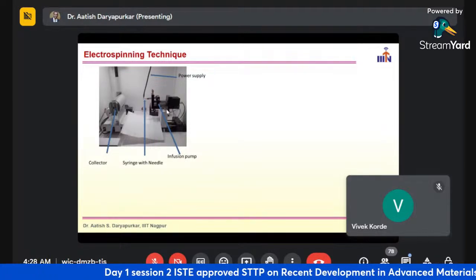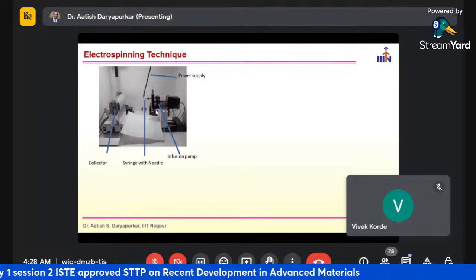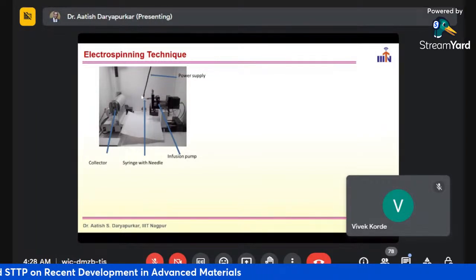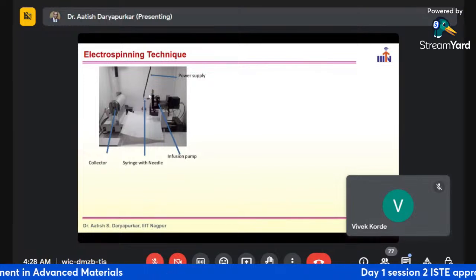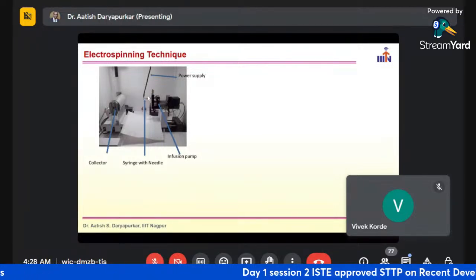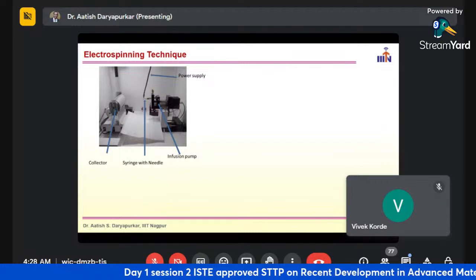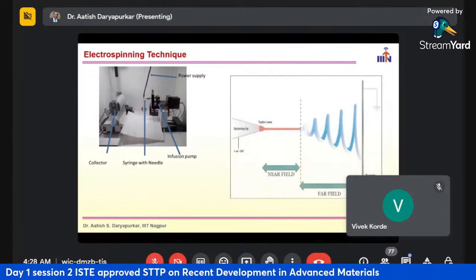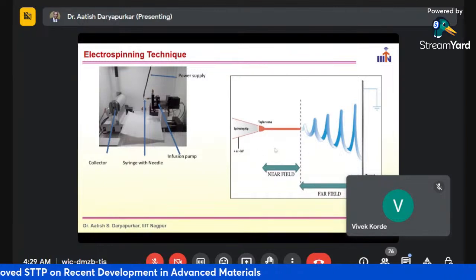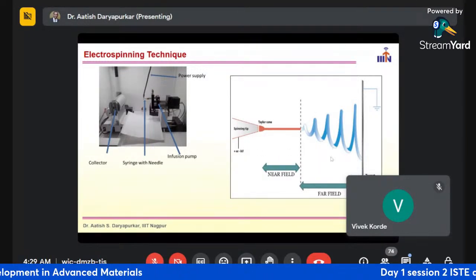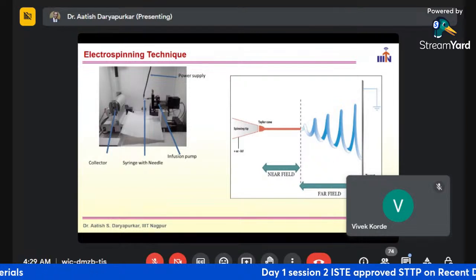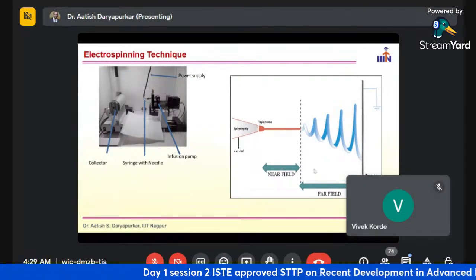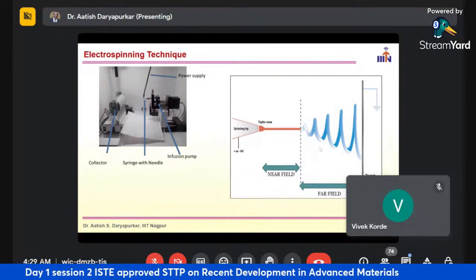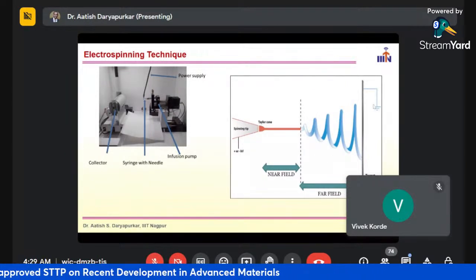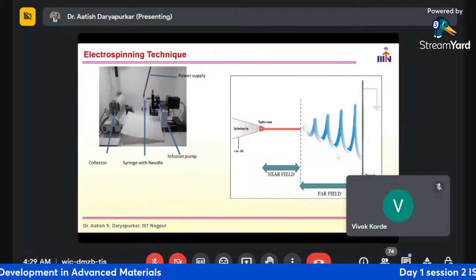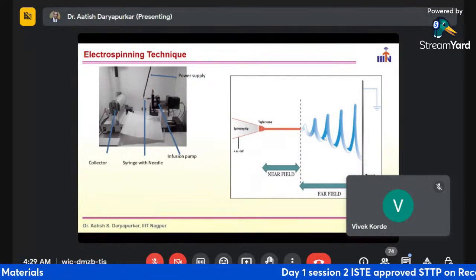Now, an electric field is applied across the tip of the needle, ranging from 1 to 50 kilovolt, which makes an electronegative drop. The surface of the drop becomes hemispherical and starts getting stretched into a cone-like shape after reaching the applied field. At this critical point, the applied electric field becomes more prominent and overcomes the surface tension of the liquid, leading to a charged jet of the solution ejected from the tip of the Taylor cone. If you see this spiral, this brown color is the Taylor cone, and this is the far field, meaning the spiral jet.